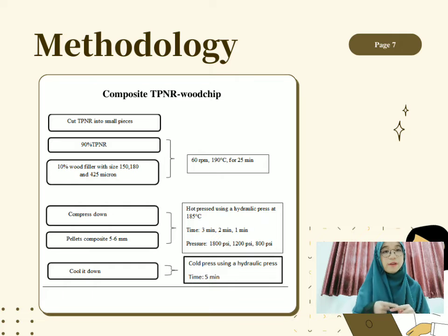The time taken for it varies: 3 minutes, 2 minutes, and 1 minute. The pressure also varies, which is 1800 psi, 1200 psi, and 800 psi respectively for the time taken. After that, we need to cool it down using a hydraulic cold press.